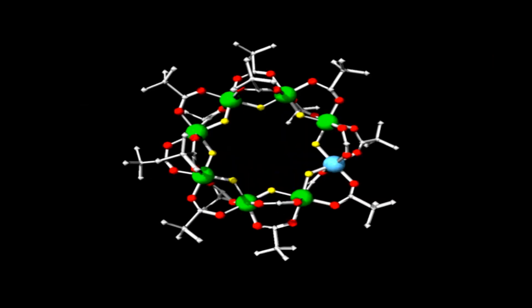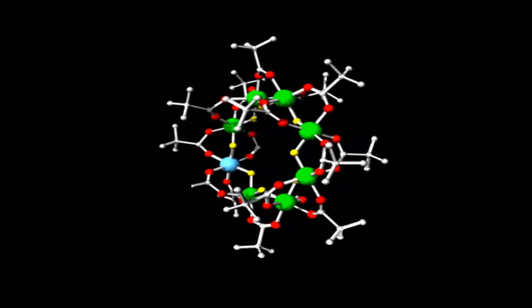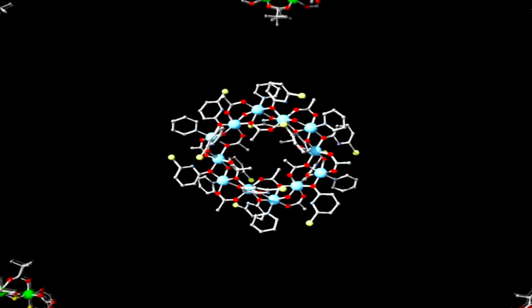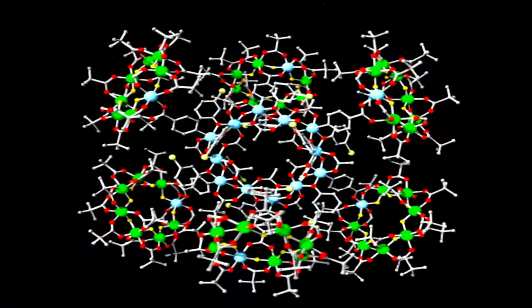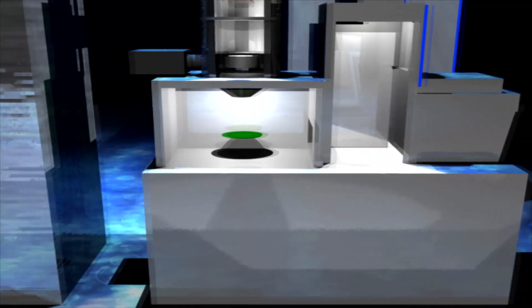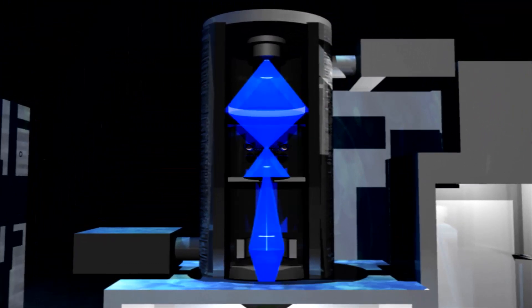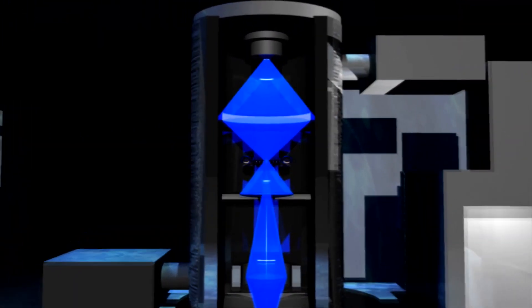My colleague makes very large wheel-shaped molecules with lots of metal ions in them and then some organic groups. These organic groups are important because they make these wheels quite soluble, and that's important because you can then dissolve them in a solution and deposit them on a surface where you want to write out your electronic circuit. And once it's dried and you've taken the solvent away, you can then etch it. And it's the etching process that is key.